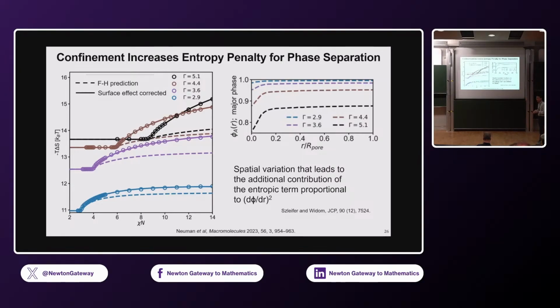The reason is, as I told you, right around the surface there are neutral interactions between A and B. So right around the surface, the polymers want to maintain a 50-50 mixture, but as the system undergoes phase separation, in the center of the pore the concentration will be far away from a 50-50 mixture. So you essentially develop a concentration gradient, and this concentration gradient now affects the entropy. So that's the effect: entropy and enthalpy now both favor the polymers staying mixed in these highly confined systems.